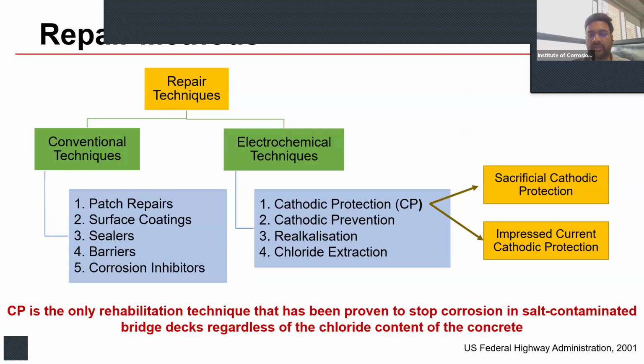In cathodic protection, we again have sacrificial systems and impressed current systems. And as per US Federal Highway Administration 2001, CP or cathodic protection is the only rehabilitation technique that has been proven to stop corrosion in chloride contaminated structures regardless of chloride content. So today's talk will majorly be focused on impressed current cathodic protection systems.